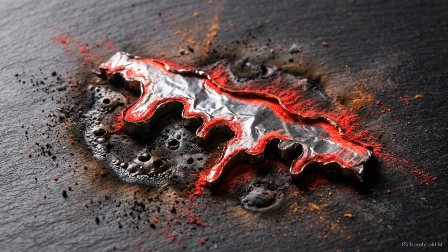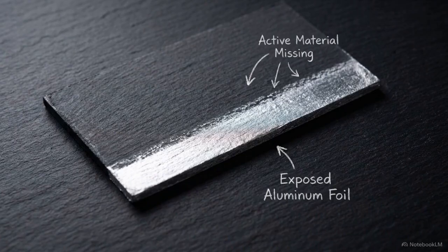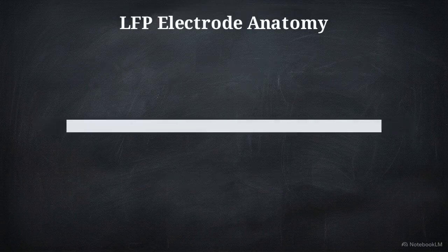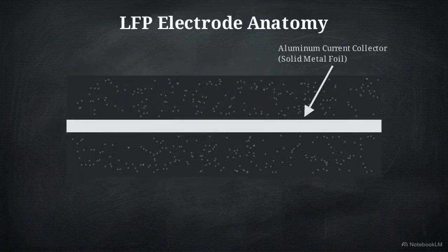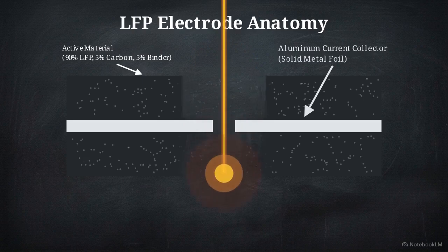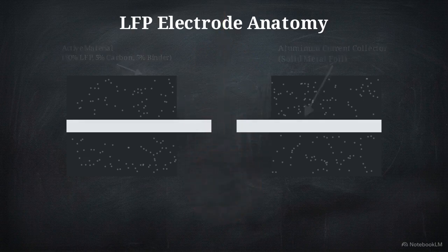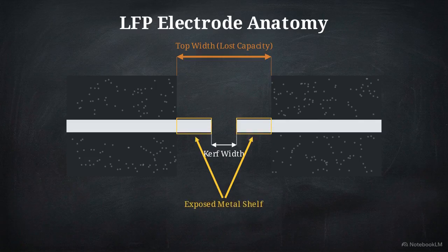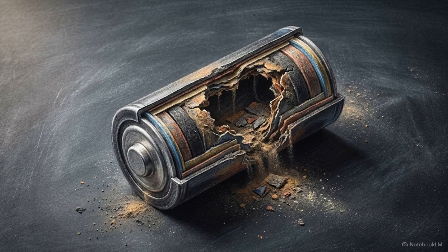But lasers introduce a new failure point: heat. The intense thermal energy required to sever the metal often vaporizes the critical active material near the edge of the cut. To understand where this damage occurs, we have to look at the anatomy of a lithium iron phosphate, or LFP, electrode. It consists of an aluminum current collector foil sandwiched tightly between two layers of active material. When the laser slices through the sandwich, any uncalibrated thermal energy destroys that active coating. Losing that material directly reduces the energy density of the finished battery cell.